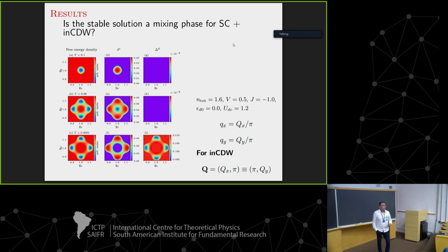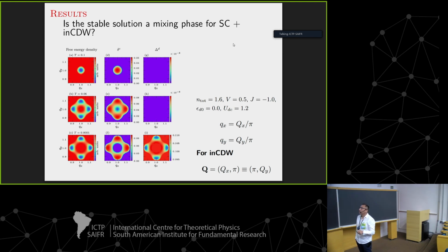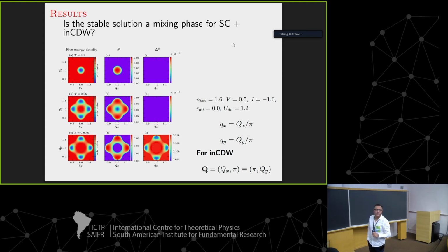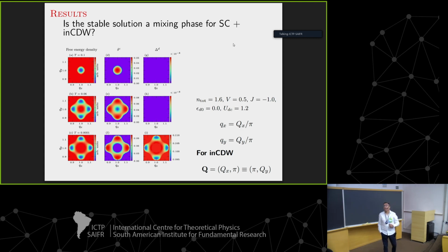Okay. If we lower the temperature, for instance, to 0.06, we observe from the analysis of the free energy density that the minimum is no longer at 1, 1 here. Okay, so it is slightly different from this value. Okay, this indicates to us that an incommensurate charge density wave occurs.